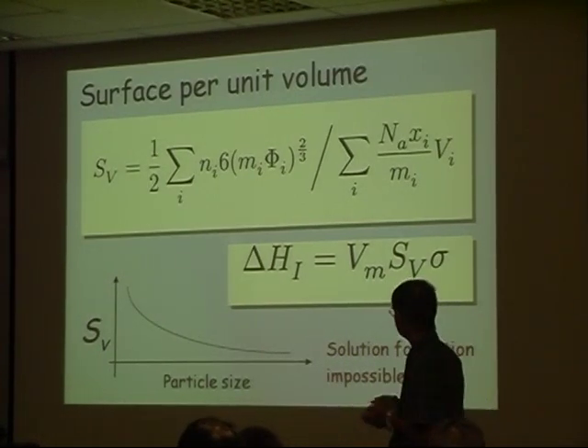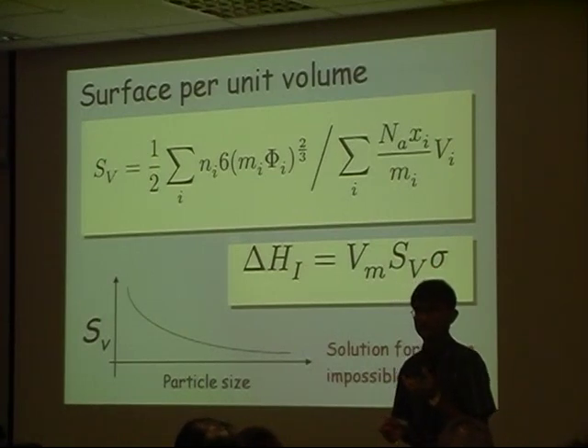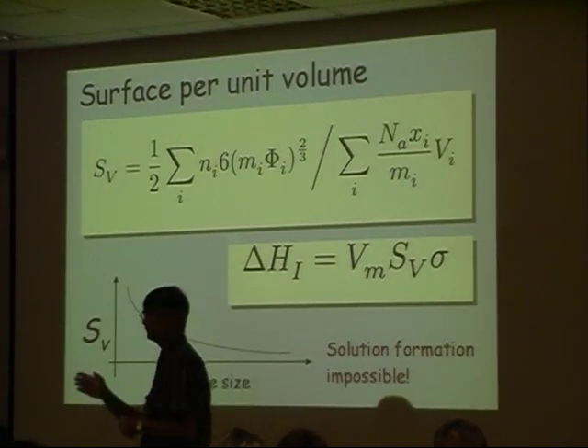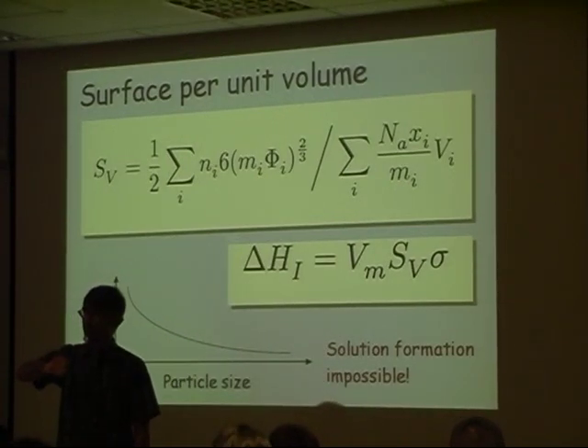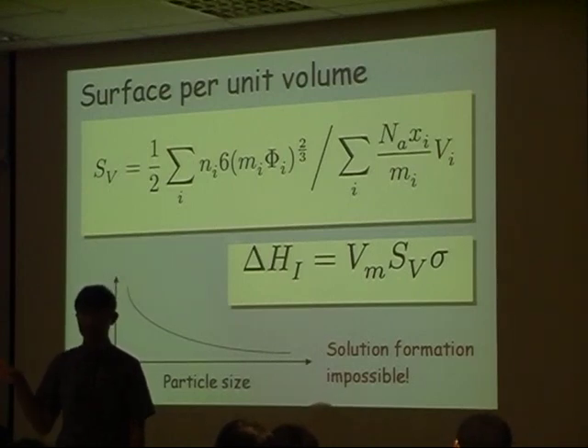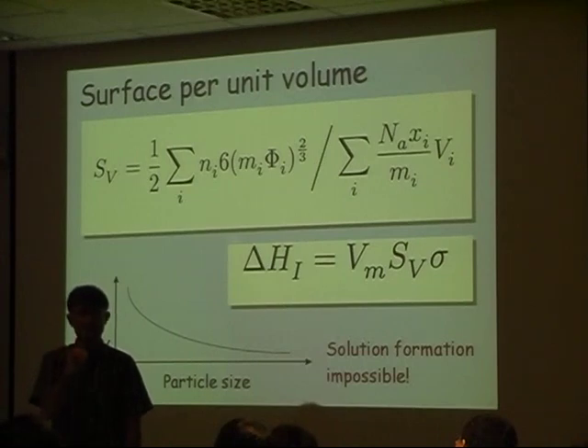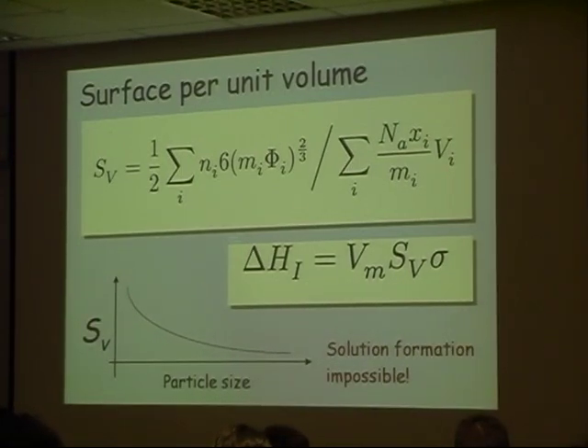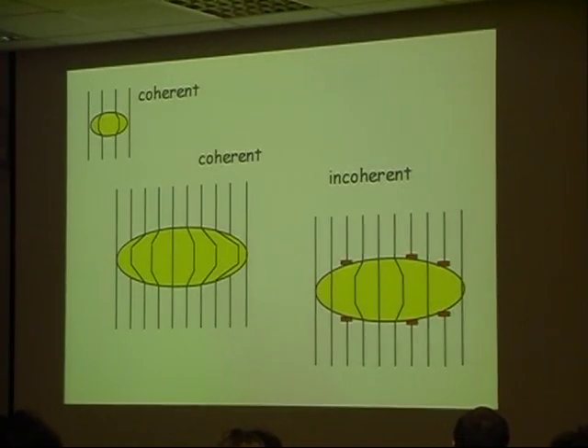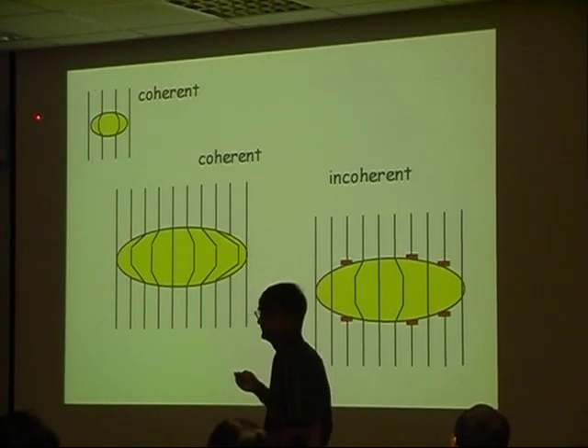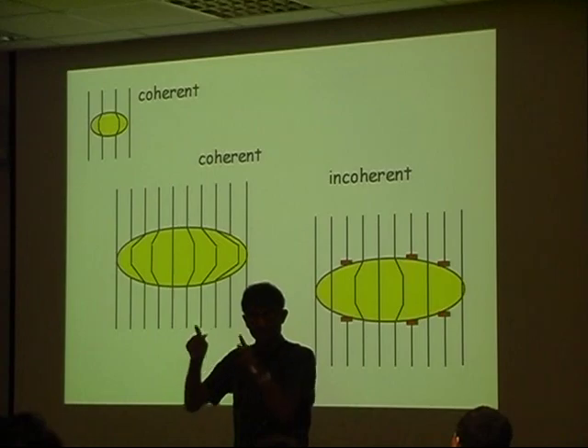What we are ignoring is that the interface energy is not constant — it changes when the particle size becomes smaller. To understand why, think of the opposite process: starting with a very small precipitate inside a matrix and allowing it to grow. When a small particle has a different crystal structure from the matrix, it will be coherent — even though the lattice plane spacing is larger in one phase, you can force them to be coherent — so the interphase energy will be small.